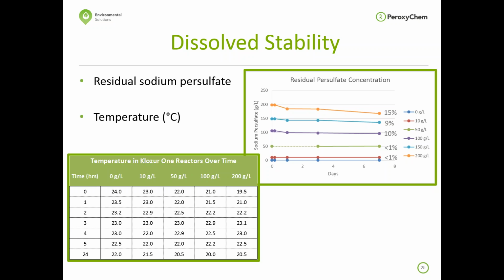7-day time frame. You get up into the 100 to 150 gram per liter range, somewhere around 10%, between 9 and 10% degraded in each one of those systems over the 7-day period. And then with the 200 gram per liter system, we saw a degradation of around 15%. We saw more degradation above 200 gram per liter, which is one of the reasons why we're trying to recommend that Klozur One be implemented no more than 200 grams per liter.